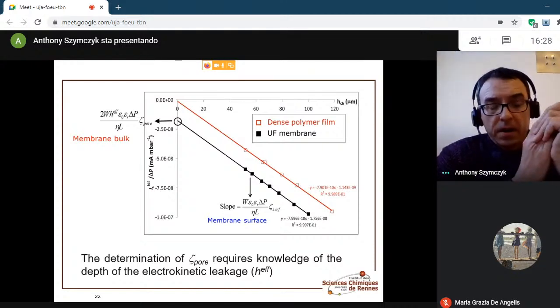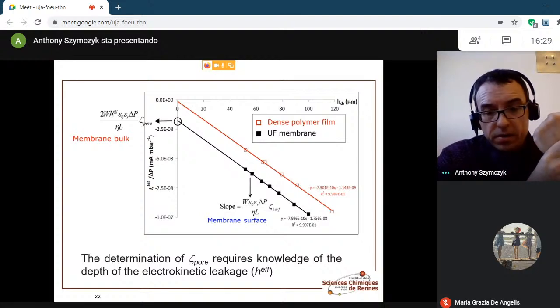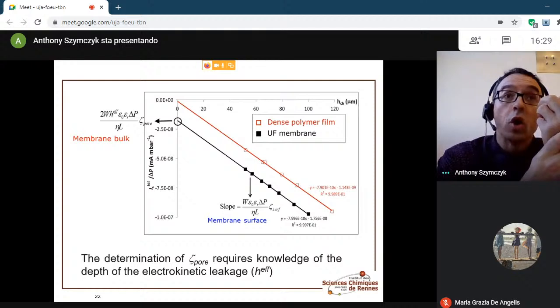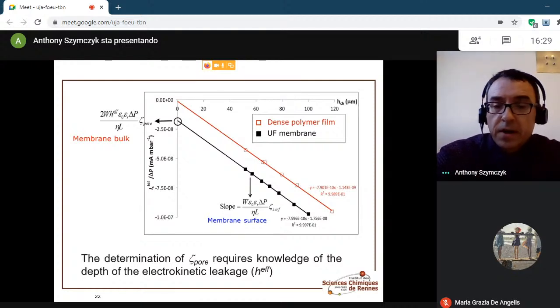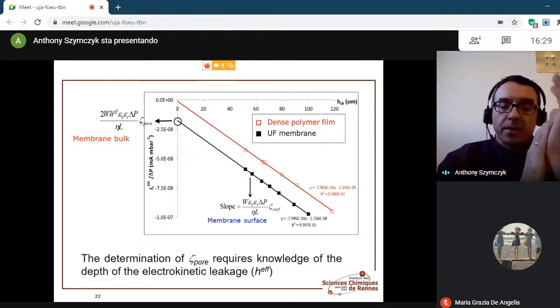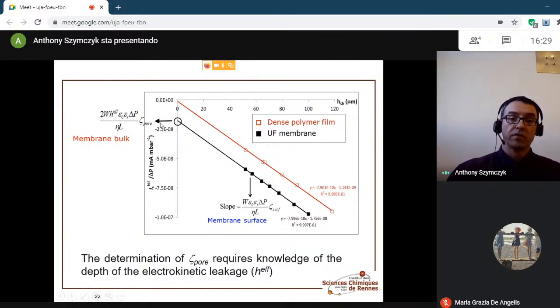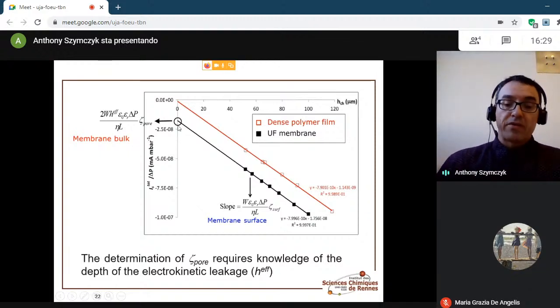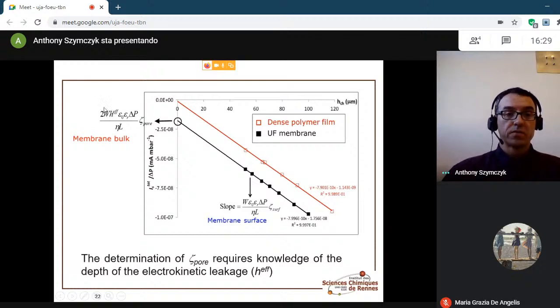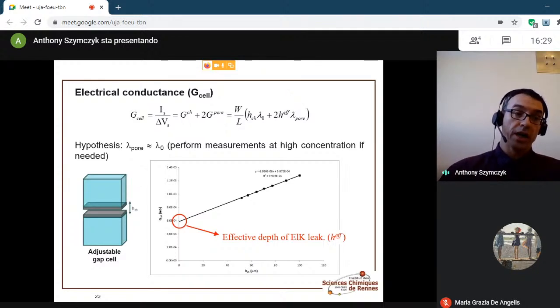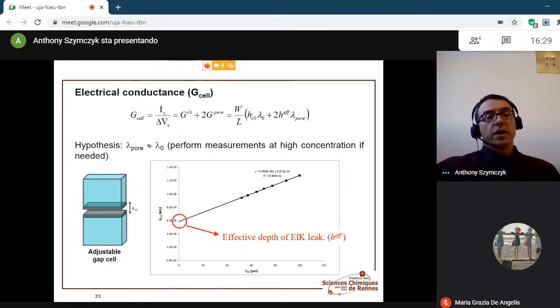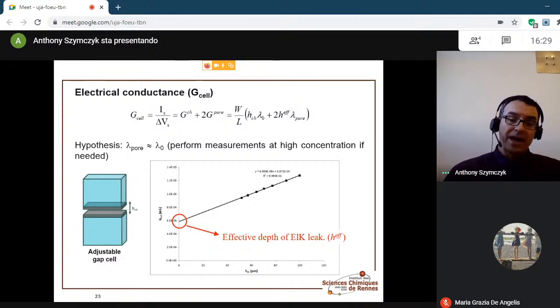As I said before, the electrokinetic leakage depends on the structural properties of the membrane matrix, but also on its electrokinetic properties. It is therefore possible to extract the value of the zeta potential of the membrane matrix from the value of the electrokinetic leakage. However, this requires the h^eff parameter to be determined beforehand. h^eff actually represents the effective penetration depth of the electrokinetic leakage. It depends on the thickness of the membrane, its porosity, and also on the pore tortuosity. In order to determine this parameter, additional electrical conductance measurements must be carried out.